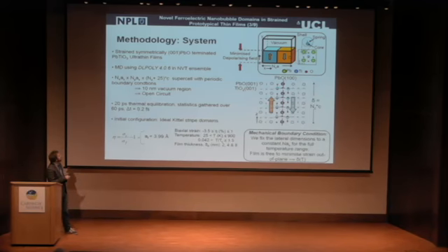That's great. And then what we do is we set up this periodic cell. We set up this vacuum region, and make sure it's large enough so that our slab doesn't interact with its periodic images. Because we have these open circuit boundary conditions, we need to make sure that our out-of-plane polarization is 0 to make sure we don't get this spurious displacement field across our system. So we initially set up a system with ideal Kittel domains facing up and down along the x direction here. So this is how we set up our initial simulation cell, the idea being that we can ramp up the temperature, cool it back down, and see what domain patterns we get.